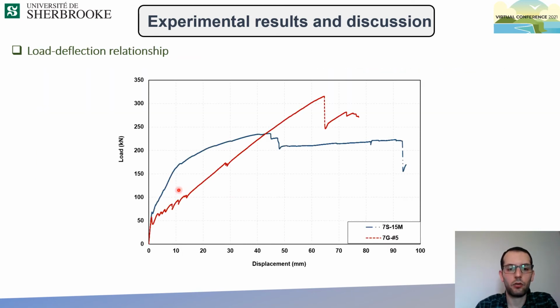Here, the load deflection relationship is presented. As you can see, the steel reinforced specimen followed a typical steel plateau. It goes after cracking to the yield, and after yield it goes with the concrete crushing, which happened in 3 stages. The GFRP reinforced specimen, after the cracking, followed a linear behavior until the failure, with higher load carrying capacity and higher ultimate displacement, which shows a good deformability of these segments. And also, from the test observations, the cracking at service load and the deflection satisfied the design criteria of the design standards.